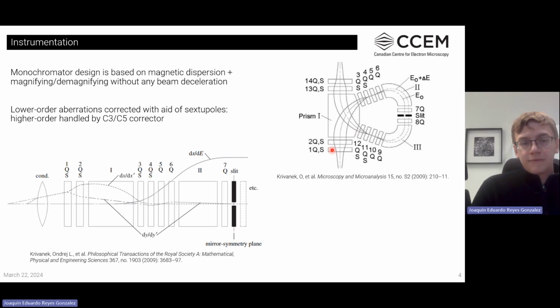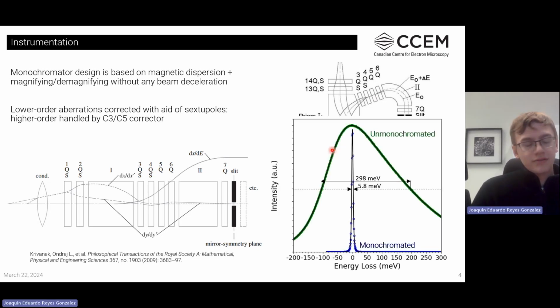Now this C3, C5 corrector - the important thing about this monochromator is that when we start here, we're at about 250, 300 millielectron volts when we enter the monochromator. When we go through this series of dispersions and we exit the monochromator, we can get down to about 5 millielectron volts, 5 or 6, pretty easily.